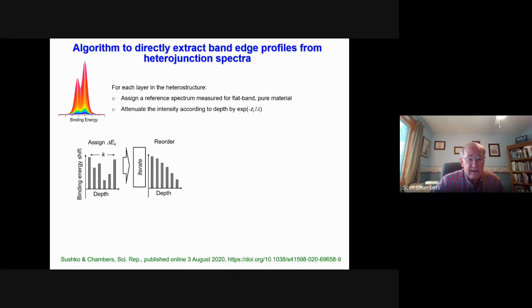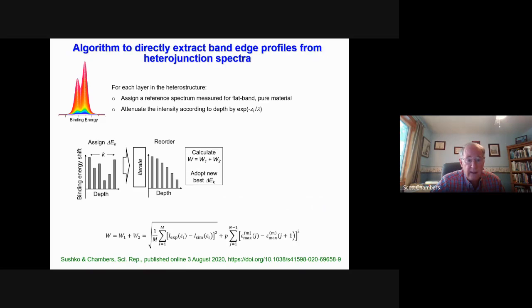We then, having assigned those monotonically changing binding energies, add up all the spectra and we fit that to the measured spectrum, and we calculate a cost function, W. And this cost function has two terms in it. The first term is a spectral fit. It's an indication of the goodness of the fit of the simulated spectrum, which is the sum over layers, to the actual experimental spectrum. That's W1. W2 is a measure of the smoothness of the changing potential with depth. That should be a smooth function of depth.